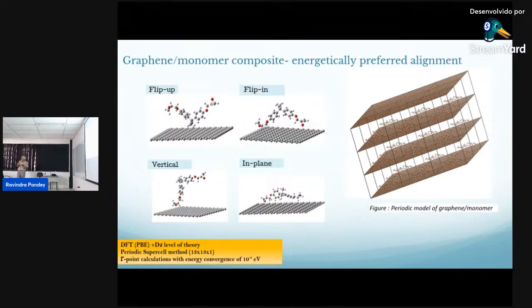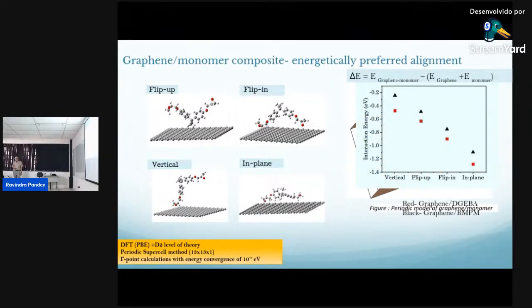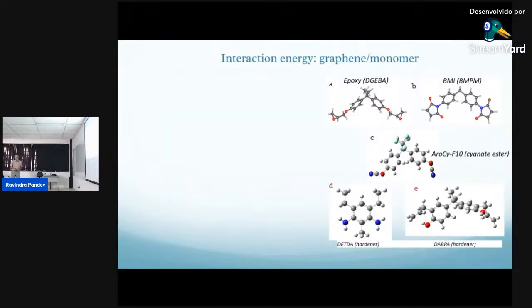Coming from physics and chemistry knowledge, we understand this configuration is going to be more stable. And the reason being is we have a larger number of atoms interacting with each other by the so-called pi electronic cloud. Calculate the so-called interaction energy versus these configurations, which is nothing but the energy of the system minus graphene and a monomer. And you can see here the in plane configuration is considerably more stable for this case.